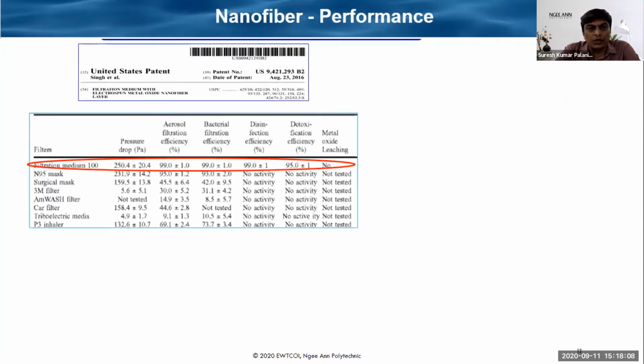The basic comparison of our nanofiber with the existing filters and face masks is that our nanofiber-based triple filter has aerosol filtration efficiency of more than 99% and bacterial filtration efficiency of more than 99%. However, the added advantage over the rest of the filters is that we have additional disinfection efficiency and detoxification efficiency. The key advantage is that we haven't found any leaching of heavy metal ions from our fibers.